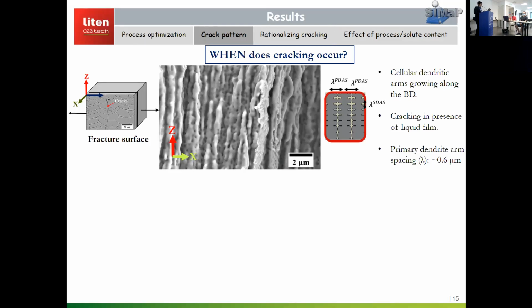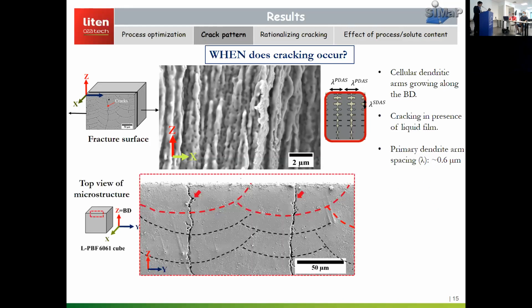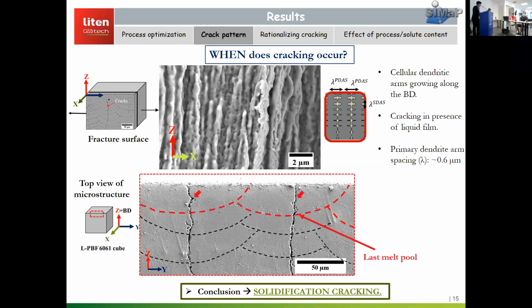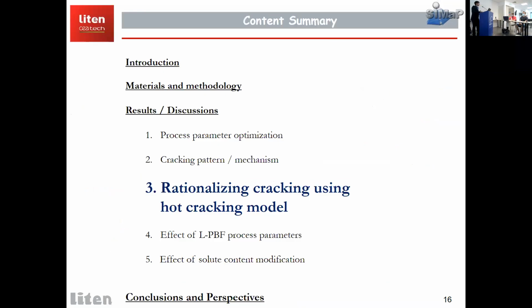This clearly indicates that cracking is due to liquid films trapped in the dendrites. Cracking due to liquid film can be due to solidification or liquefaction. Solidification cracking can occur during the last stage of solidification, or liquefaction can be due to remelted melt pools, for example. To resolve this ambiguity, we looked at the final melt pool, the topmost melt pool regions, which are not remelted. We clearly see that cracks in the last melt pool are occurring, and this suggests that cracking is due to solidification. Okay, now we have identified where cracking occurs: along high angle grain boundaries, at the center of the melt pool.